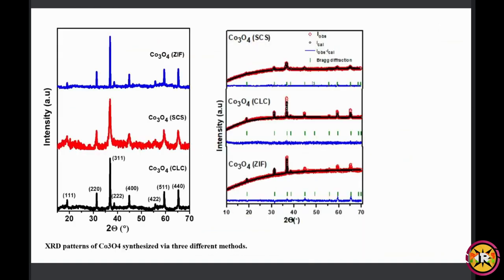So I have done the XRD, and this figure 1 is the XRD pattern of the three synthesized Co3O4. From here we can see CLC denotes the cobalt oxide synthesized from the cobalt nitrate, SCS denotes solution combustion synthesis, and ZIF denotes from ZIF-67. What is the difference here? As we can see clearly for CLC and ZIF, the XRD pattern is intense, while for SCS, the peak is broadened. So from here we can say the crystallinity of CLC and ZIF is more than the SCS, and